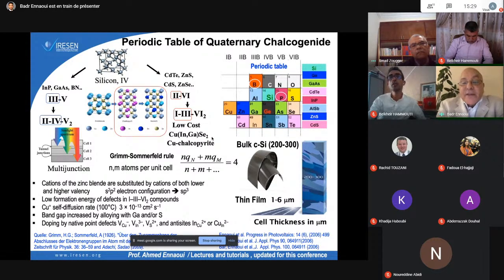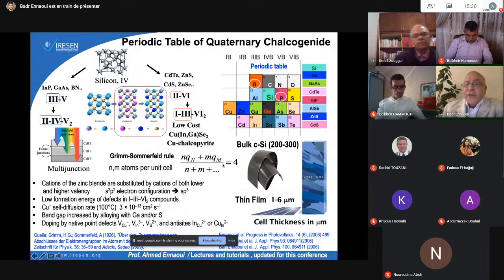That's why it's extremely difficult. Of course, when we move from silicon to the binary and ternary compound, we move from bulk material to thin films. And you see, for a silicon solar cell, you need at least 200 to 300 micrometers to make a solar cell. However, for thin film, you need only 1 micrometer, maybe up to 6 micrometers. So you see how much material you will save, and therefore you will gain in the cost.